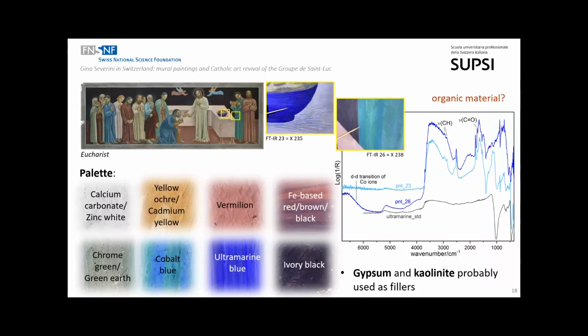For the Eucharist scene, this is a summary of the different pigments found in these wall paintings. You can see, for example, the identification of another blue pigment, cobalt blue, identified by X-ray fluorescence, but also thanks to the collection of the FTIR spectrum that is characterized by this particular form. Here I reported an example. And also gypsum and kaolinite, probably used as filler, in particular in the ochre and earth pigments.